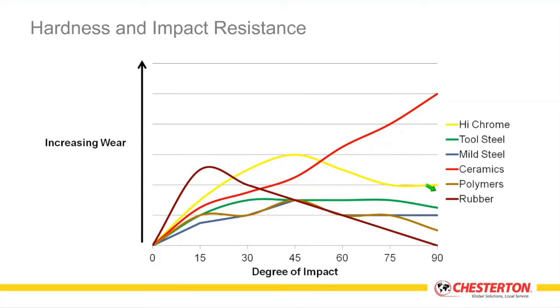Other materials tend to be more wear hardening in effect. And then you see your polymer-based systems performing roughly in the same range as the rubber range. It depends upon the type of polymer that is being chosen. But ductility in this instance becomes the more primary driving force to resistance and wear.